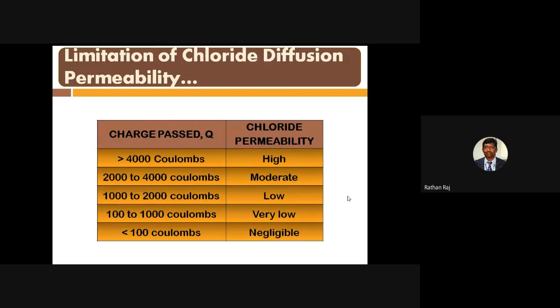So what are the limitations? The coulomb value, the charge passed Q value, is calculated in coulombs. If more than 4,000, we can conclude that the chloride permeability is very high. 2,000 to 4,000 is a moderate value. 1,000 to 2,000 coulombs, the chloride permeability is low, and 100 to 1,000 coulombs, it is very low. When it is less than 100 coulombs, it is negligible. There is no chloride permeability.